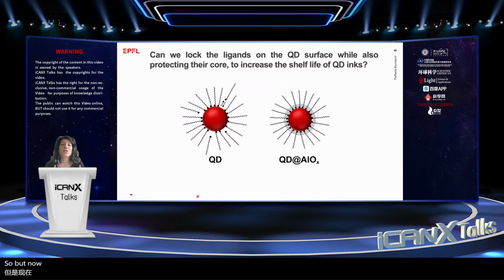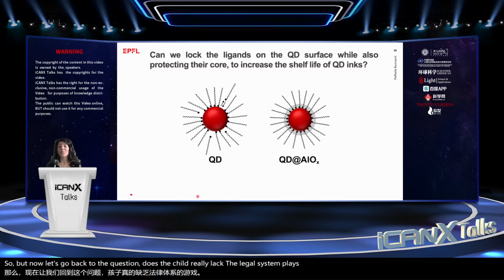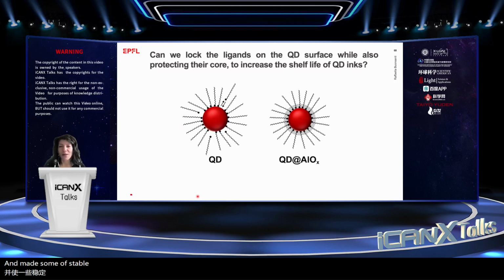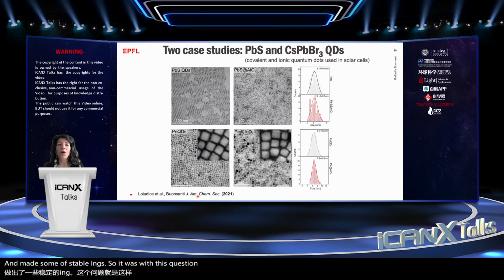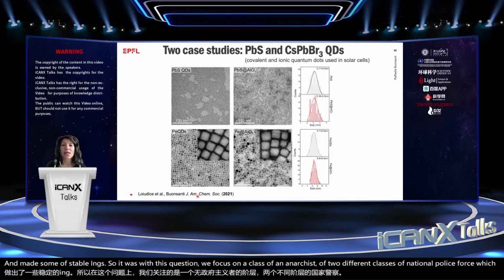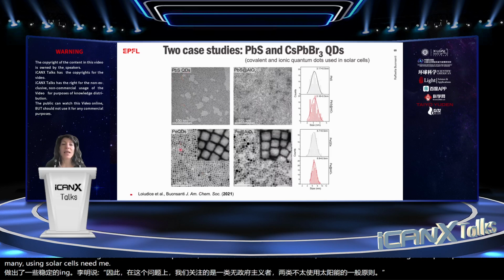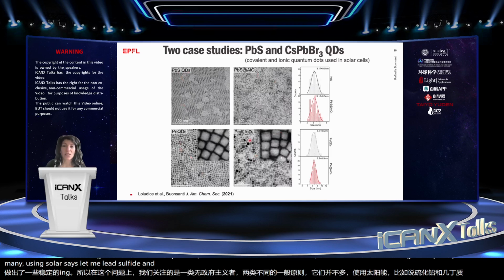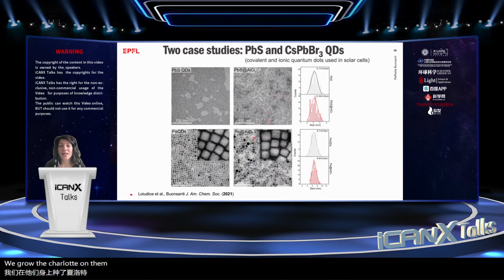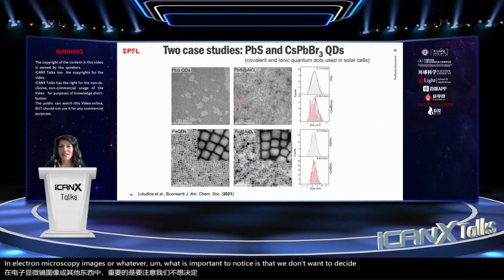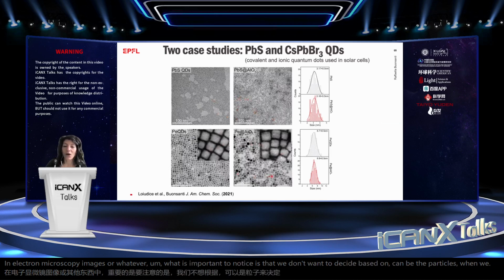So, but now let's go back to the question. Does this shell really lock the ligands in place and make more stable inks? To answer this question, we focus on two different classes of nanocrystals, which are normally used in solar cells, namely lead sulfide and perovskite nanocrystals. We grow the shell around them. Again, it's not possible to visualize it in the electron microscopy images. However, what is important to notice is that we don't modify the particles when we grow this oxide shell.